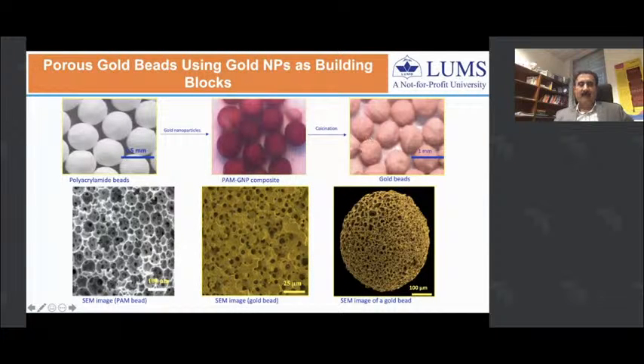This is another kind of strategy in which we used gold nanoparticles as building blocks to make new materials. For example, in this case, these are polyacrylamide beads, which are hierarchically porous. You can see these macropores, and within these bigger pores, there are smaller pores. So it is basically a hierarchically porous polymer bead. When we soak this in gold nanoparticles, these were the acrylate stabilized gold particles.